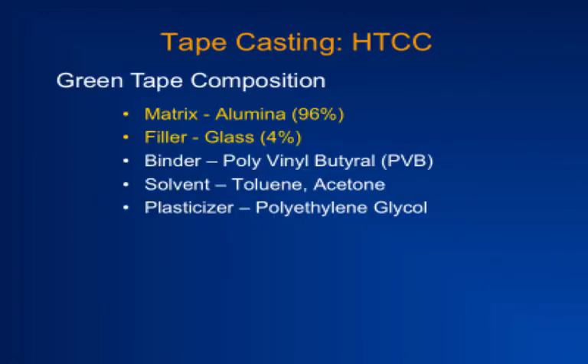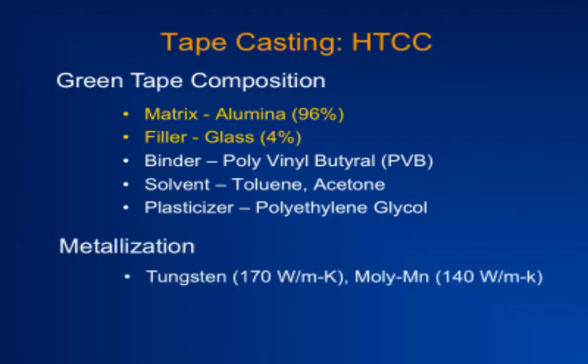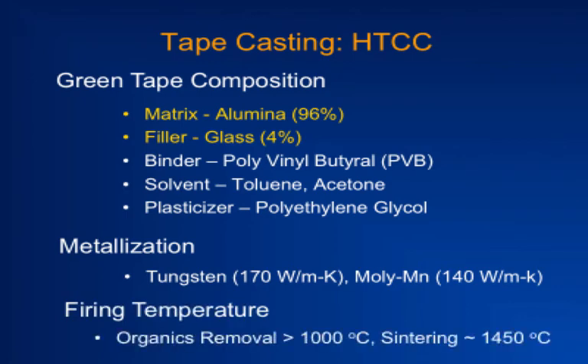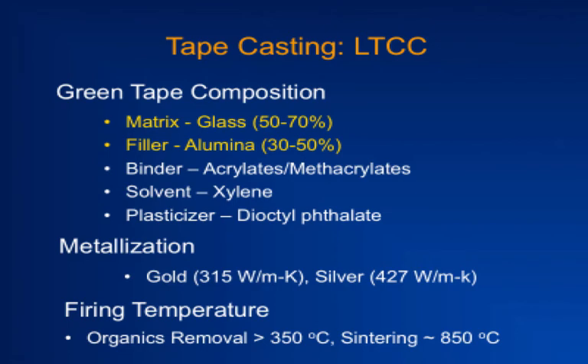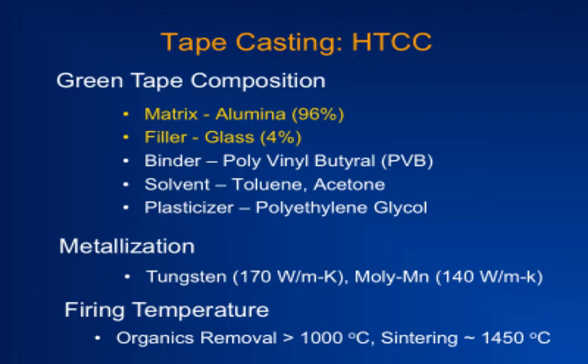The temperature, so high temperature, depends upon the amount of glass that is there in the alumina. Glass melts at a lower temperature. These are some kinds of polymer additives that are present, right? The metallization, because it can be fired at a higher temperature, tungsten and molybdenum can withstand high temperatures, okay? And they can also dissipate heat much more readily. So typically you sinter around 1450 degrees centigrade. If you increase the amount of glass, you can fuse this material. You can sinter it at much lower temperature compared to that.